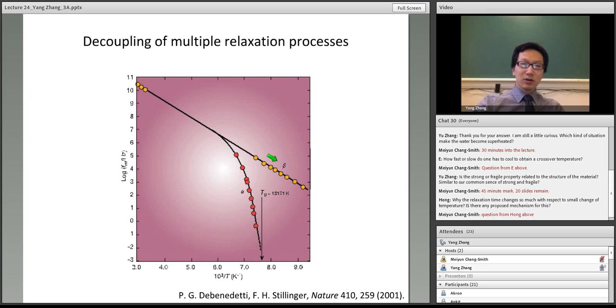It's pretty common for glass-forming liquids, when approaching the glass transition temperature, that the relaxation splits into two processes, alpha and beta. To make it clear, these alpha and beta are not exactly the same as the previous alpha and beta in the intermediate scattering function. This splitting of the alpha and beta relaxation times is observed in dielectric spectroscopy.